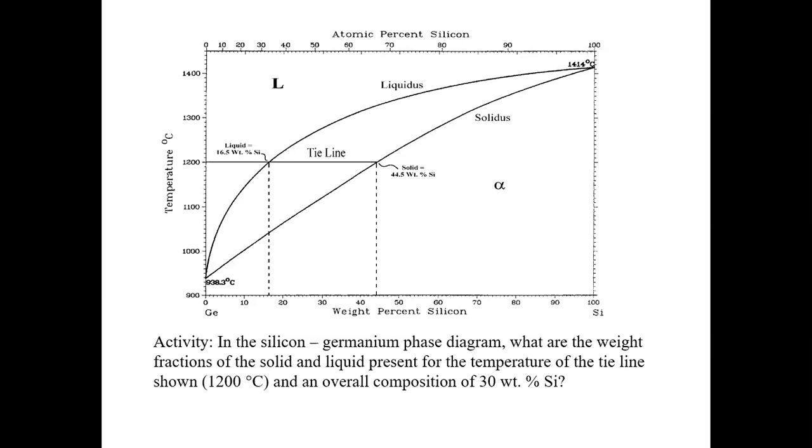Okay, so now I'm going to speed up a little bit because I hope this is already clear to everyone. So let's look at a more complex scenario. This is, I would say, probably the simplest phase diagram you can ever have for an alloy because it only has a single liquid region, a single solid region, and a solid-liquid coexistence. But in general, for an alloy, you would have at least two different solid phases because usually the two elements that are mixed together have different crystal structures, right? One example for that is the lead-tin system.